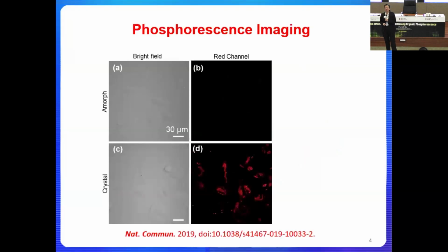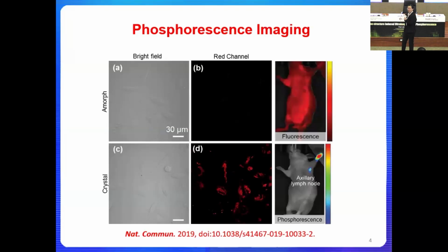Now, in 2019, we discovered a method that allows us to manipulate the organic molecules into either amorphous nanoparticles or simple organic crystals. And once we were able to differentiate the molecular aggregates into amorphous or crystallized states, we were able to conduct cell experiments and later on animal experiments. What we observed here was that in terms of the background signal, if the molecule is in the amorphous state, it is not able to show phosphorescence at room temperature in the aqueous media, so you don't see background signal, but you also don't see any real signal from the molecule. As a consequence, you will see very bright fluorescence at the background from the animal by itself.